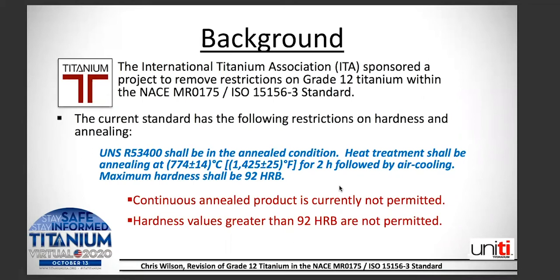So the restrictions there are that the annealing requirement requires a batch annealing furnace. So continuous annealing product is currently not permitted by that statement. Also, hardness values greater than 92 HRB are not permitted. There was some thought that that was too low of a hardness for grade 12 with the increased tensile and yield strength, and that really the hardness didn't have a real effect on the corrosion properties for these titanium alloys.